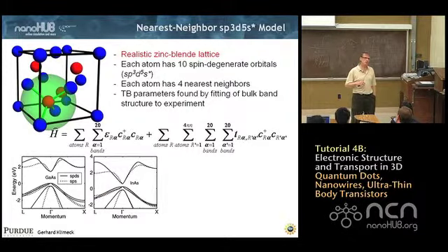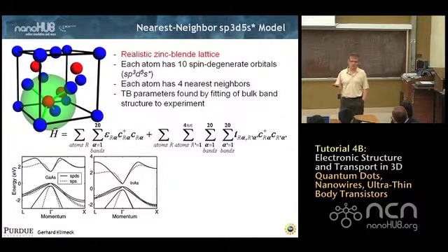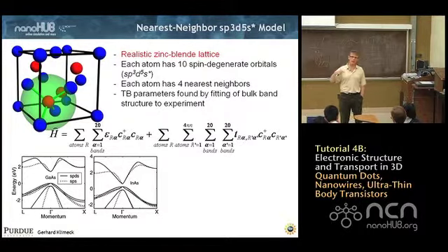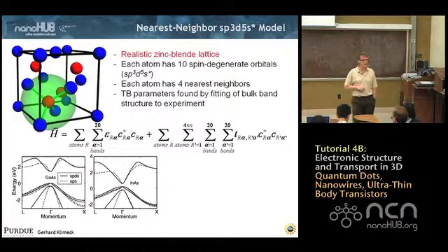Yeah, so then the approach we take is we fit these material parameters once against bulk. And we do as good a job as we can, and we assume in the systems where we'd like to apply them, there are no bond changes, no rebalancing of charge, and then we model the nanostructure with this basis from bulk, which is a deep dive, right? You take a jump off a cliff and you hope it actually works. And if there's no bond redistribution, if there's no chemistry changes, it actually works quite well. And I'll show you examples of that later.